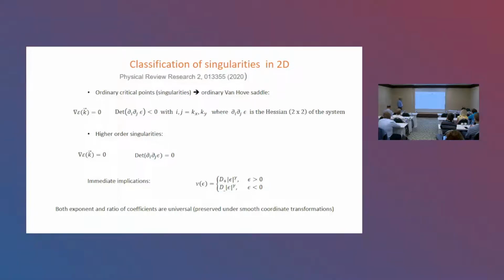So, a bit about the classification of singularities. The gradient of the dispersion relation has to be 0 in any case in order to see something very interesting in the density of states, diverging if you like. Then it depends on what happens to the Hessian. In 2D, it's a 2x2 matrix of second order derivatives, and we form the determinant of that. If it's negative, then we have the ordinary critical point, the ordinary Van Hove singularity that leads to logarithmic divergence in the density of states.